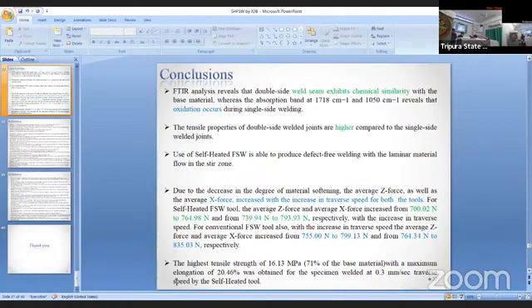For the Self-Heated FSW tool, the average Z force and average X force increased from 700.2 Newton to 764.98 Newton, and from 739.94 Newton to 793.93 Newton, which is very significant, as you can see, with the increase in the traverse speed. And for the conventional FSW tools also, with the increase in traverse speed, the average Z force and average X force increase. So the highest tensile strength of 16.13 megapascal, that is 71% of the base material, with a maximum elongation of 20.46% was obtained for the specimen that was welded at 0.3 mm per second traverse speed by the Self-Heated tool.